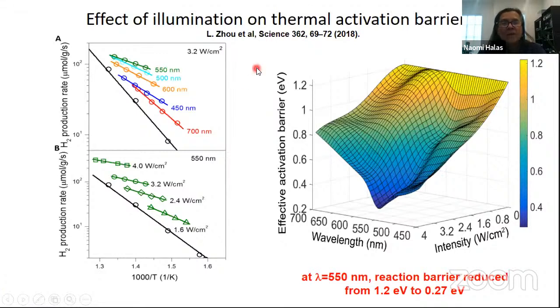So as I said, we lowered the reaction barrier. So if we look at the black lines here, all we're doing is measuring the reaction barrier to ammonia decomposition. These black lines show me what the reaction barrier is in the dark, right? The slope of this line gives me the reaction barrier. And then if I begin to shine light, I find that as I shine light, I change the slope of this line, right? As I'm lowering. So I'm measuring this at several different temperatures, right? I measure the reaction barrier to get the slope of the line.